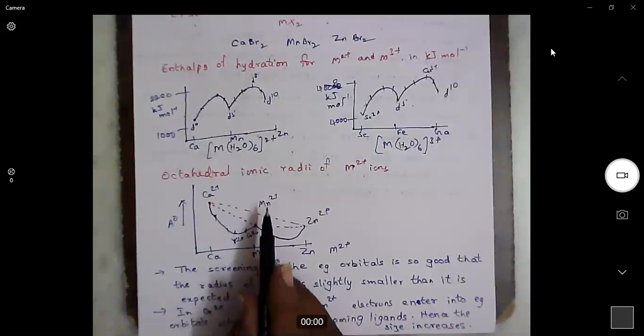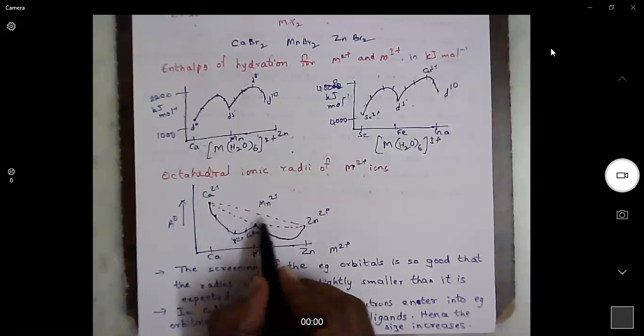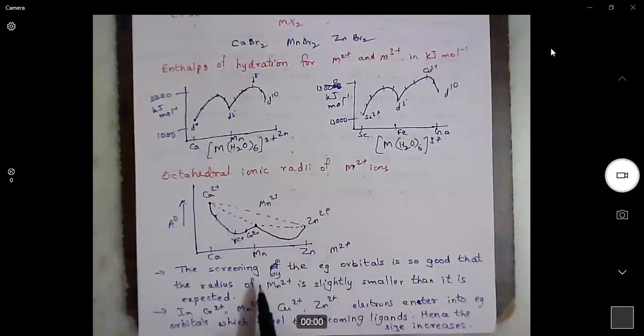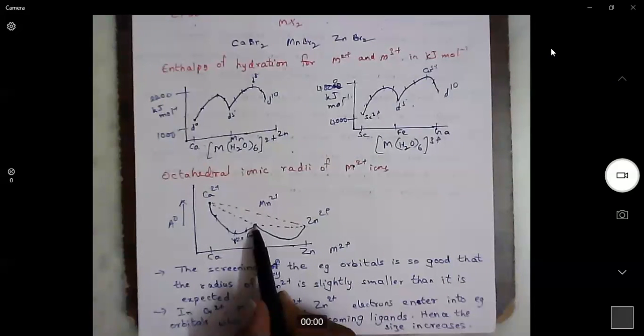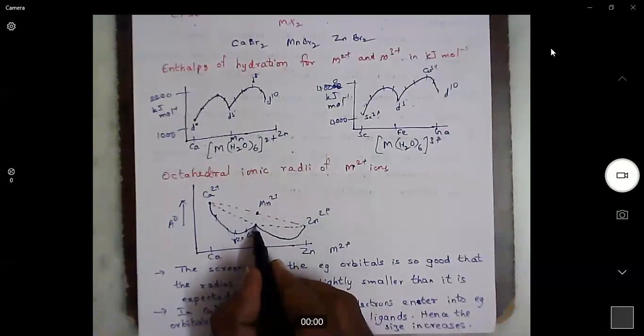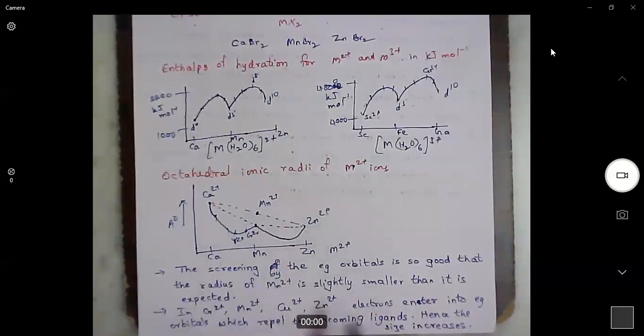But in the case of manganese, it is supposed to be here, but it is not here, right? It is the actual versus expected size. This is because the screening by the eg orbitals is so good that the radius of Mn2 plus is slightly smaller than expected. Why is the size of Mn2 plus smaller than expected? If it is at this point, then it is expected. But actually it is here. That means size is smaller than expected. The reason is that eg orbitals are better at screening. Because of the eg orbital screening, we observe a smaller size for manganese 2 plus than expected.